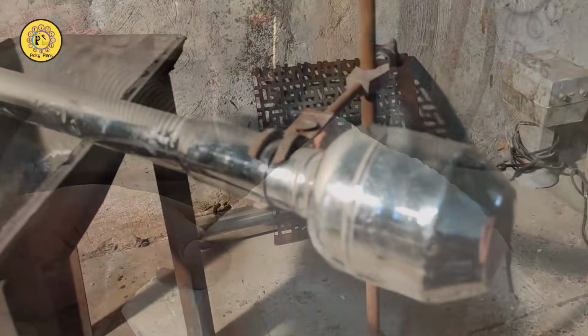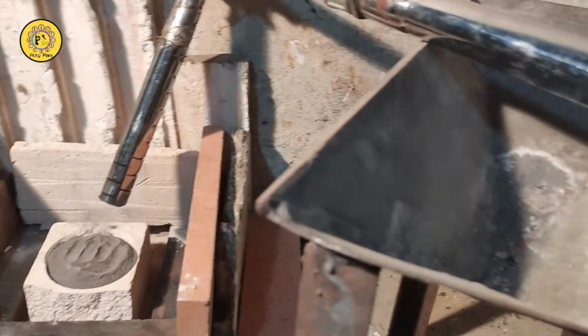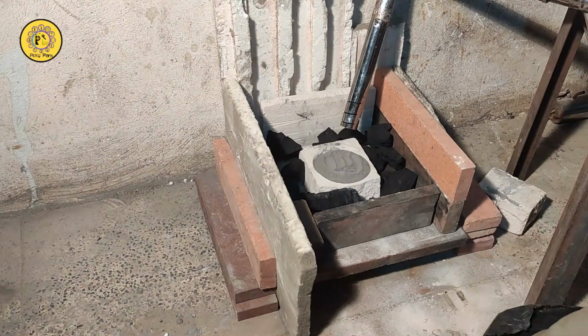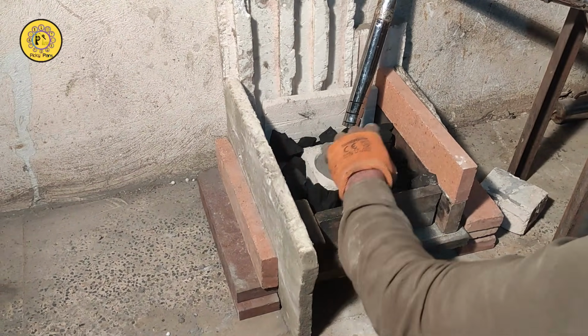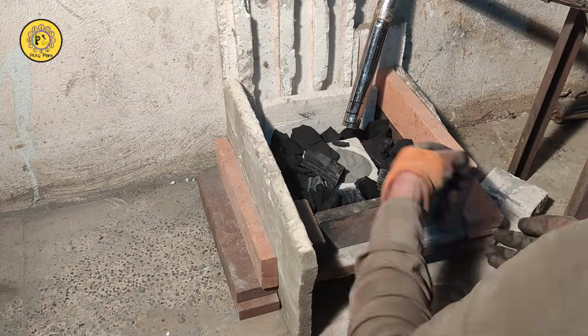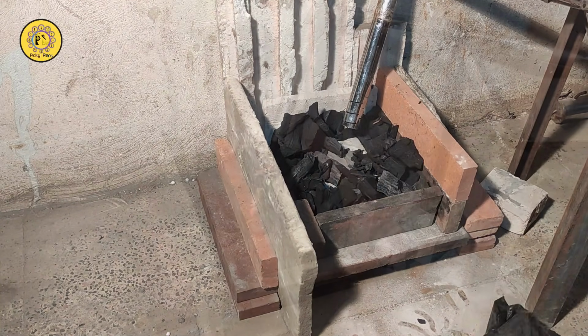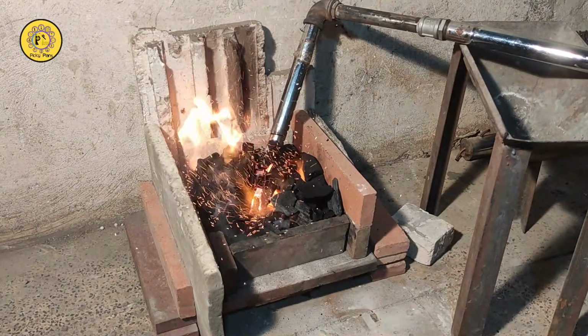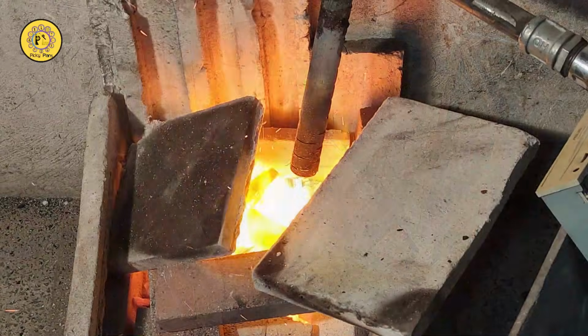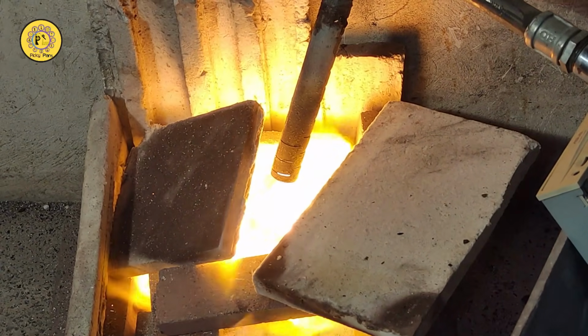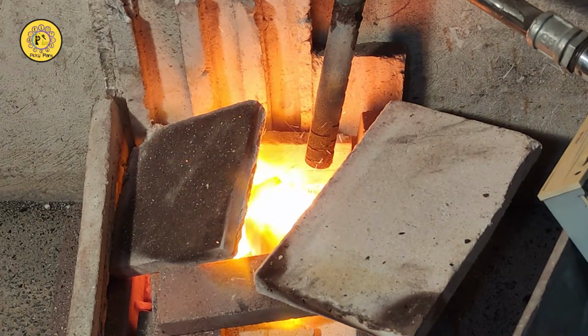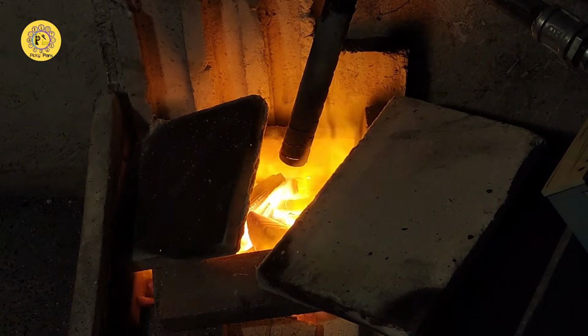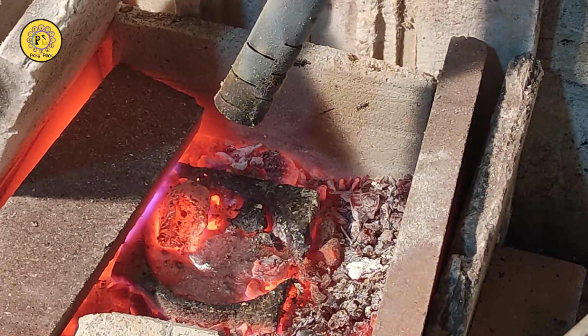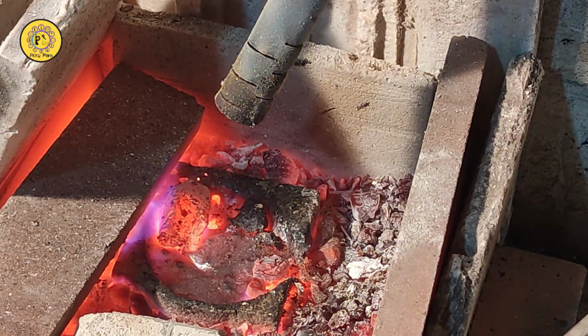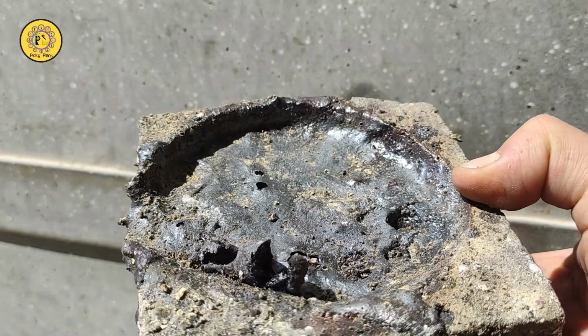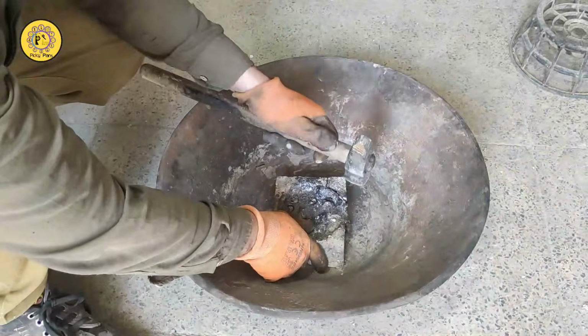I attempted to fuse the mixture using charcoal. To ensure everything melted properly, I needed to heat it up to 1200 degrees Celsius. At first glance, it appeared completely melted to me. However, upon breaking the melting dish, I observed that only the top of the charge was properly subjected to the heat.